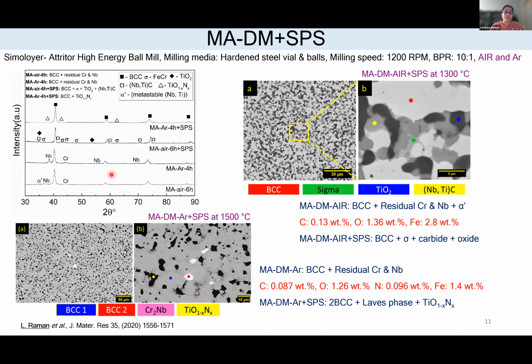We may think, why in this case couldn't chromium react with iron and form a sigma phase? Because when we did it in argon atmosphere, we reduced the milling time, and it had only about half the iron contamination. So it's not sufficient to form a sigma phase. Also, the oxygen content in this scenario was very low. So rather than TiO2, we had a titanium oxynitride phase, and we had two BCC phases, one niobium rich, and the other multi-component in nature. So in the dry milling scenario, depending on the milling atmosphere, we have two different kinds of secondary phase.